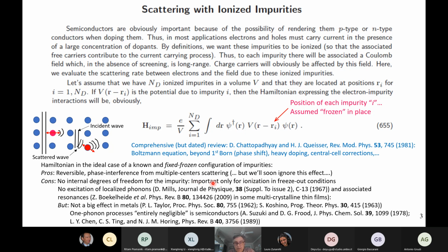For example, there are lots of papers dealing with the effect of impact ionization in impurities in freeze-out conditions. For silicon, freeze-out, even in heavily doped silicon, say 10 to the 20, is at very low temperature, about 20 Kelvin or so for, I think, 10 to the 19 per cubic centimeter. So low temperature may be interesting, but at room temperature or higher, which is the temperature at which a chip operates, this will not usually be an issue, and exciting core levels or valence states of the impurity clearly requires energies which are beyond what we're interested in for transport.